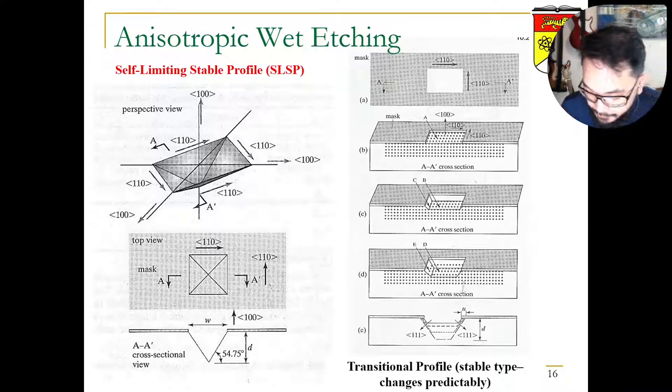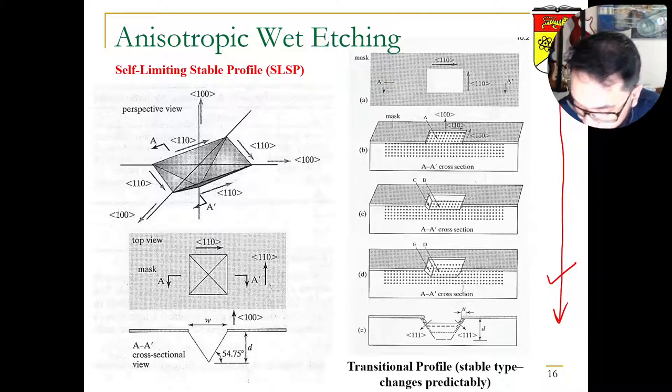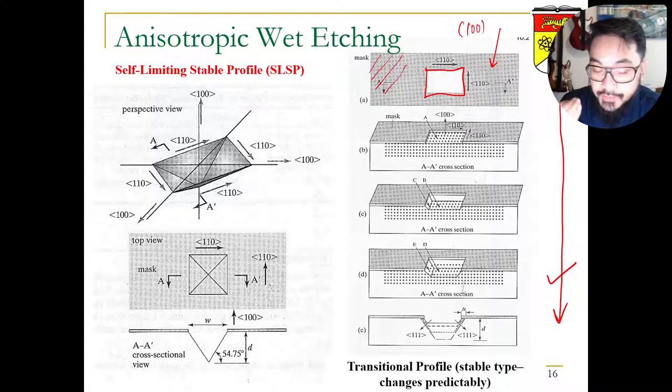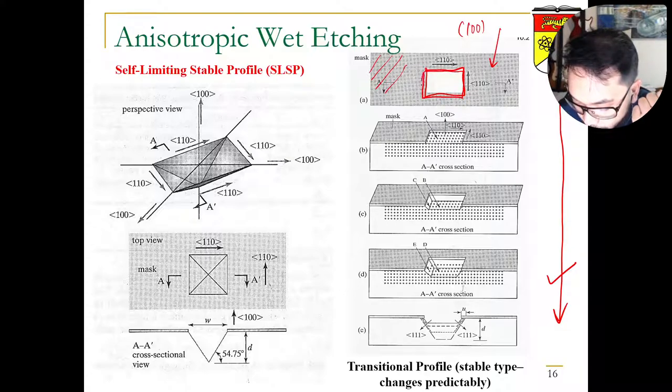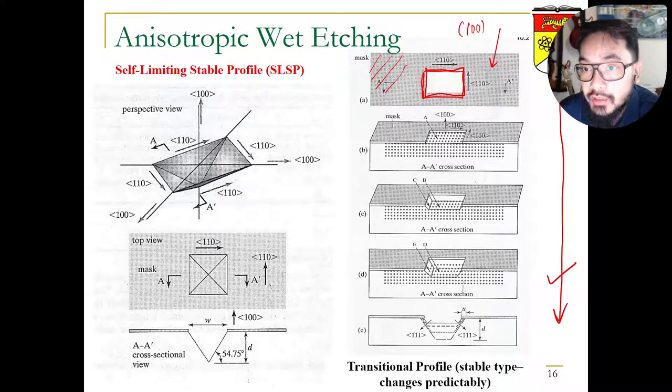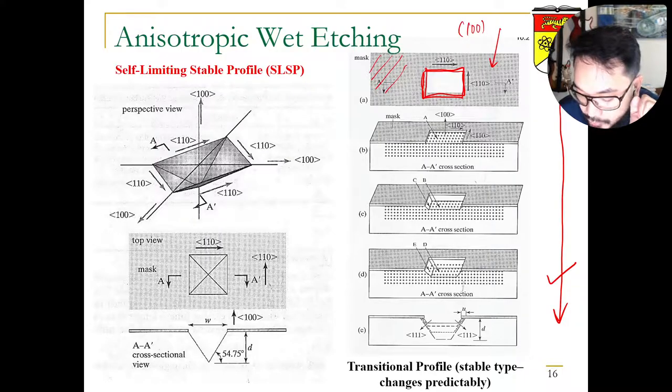Okay, now let's look at this picture here on the right hand side first. So you go through the process here. This is looking at the top. If you look from the top of your wafer, let's say you have an opening which is more or less a square. If this wafer is a 100 wafer, that means looking from the top, the plane that is looking right back at us is the 100 plane. Then you can align your opening with the 110 plane direction. So where is the 110 direction on a 100 wafer? The 110 direction is basically parallel to the surface, and then 90 degrees to that is also another family of 110. And you can align the opening mask